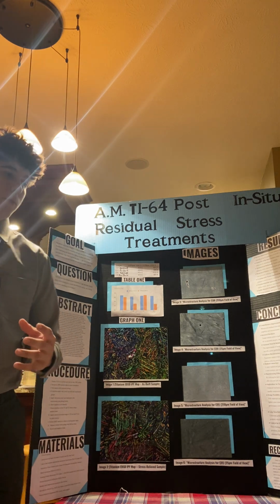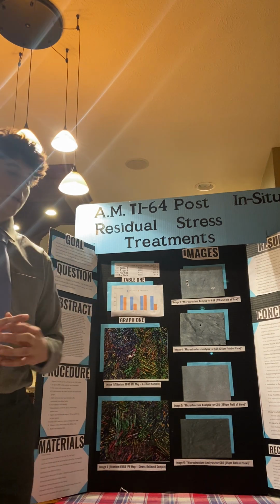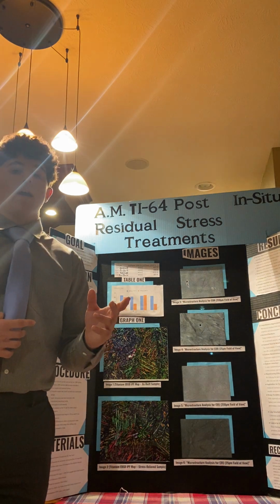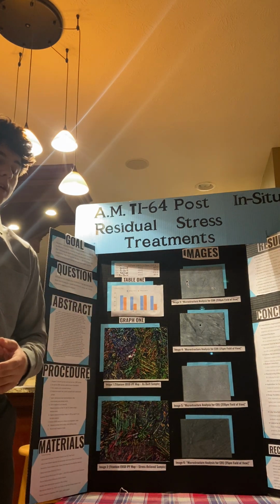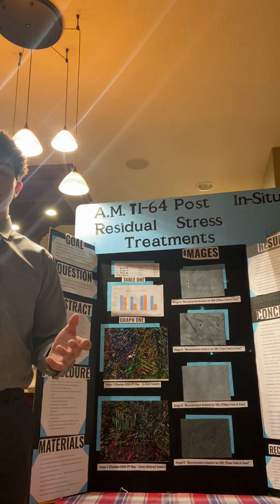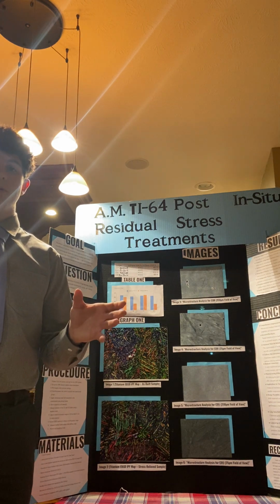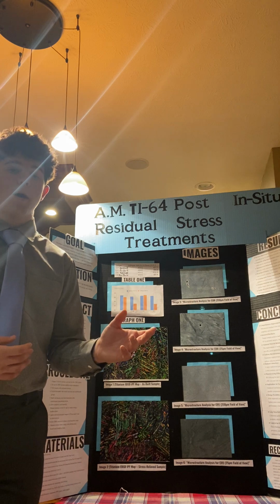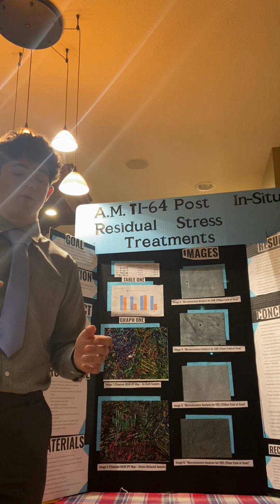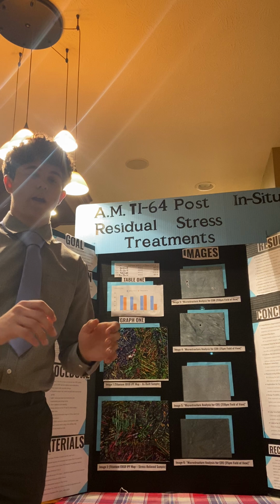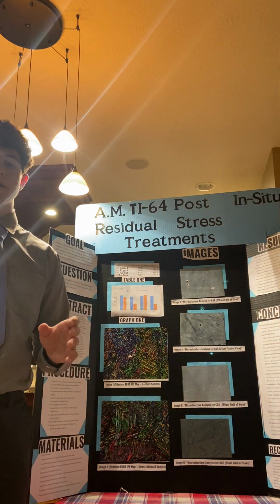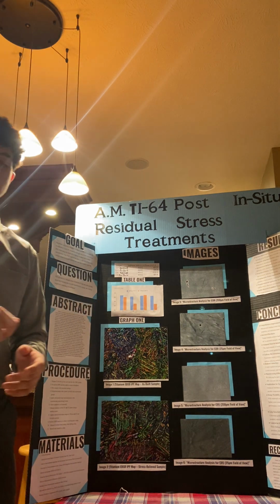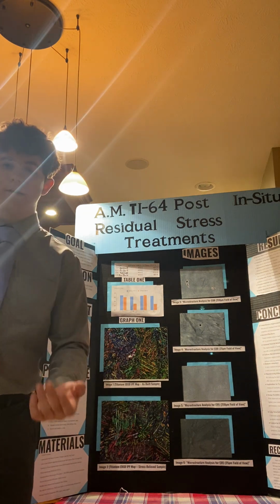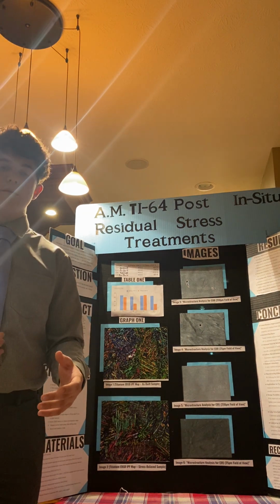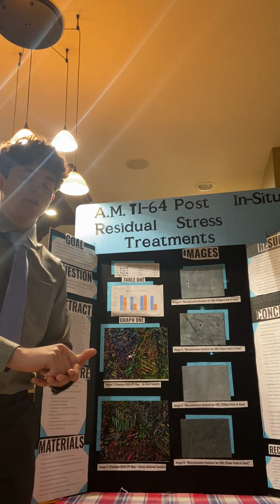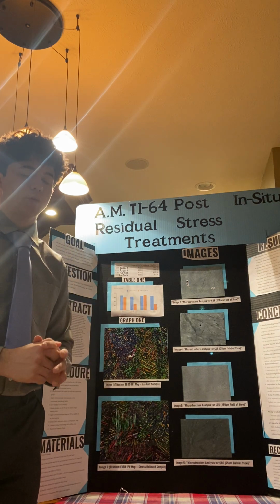And then after I printed the metal and cut it, I then polished it. How the polishing works is first you mount the metal in epoxy resin. You put it into a chamber, and it compresses it and heats the epoxy resin to the metal at a really high temperature. It's so that you can grip the metal as you polish the material, which I'll get into in a second. To polish the material, you hold the epoxy resin, which you just melted to the metal, and you're going to have one surface of the metal exposed.